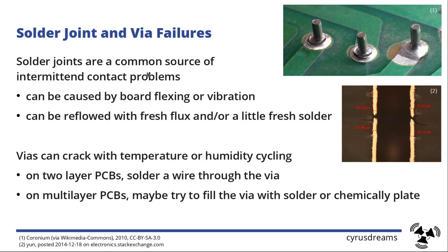The PCB board itself, it can also have some quite annoying failures. You have the solder joints everywhere, and over time, if there is vibration present or it's a very heavy type of component on the top side here, you get cracked solder joints. So you have these lines running around the whole solder joint. So that one on the right hand side, that's actually still connected. You do have something different here. You have pad lifting. You see that maybe that pad got lifted off from the PCB, but those two definitely are cracked through. You can fix that quite easily with a soldering iron. You just reflow that with fresh flux and maybe a little bit of fresh solder here, and the solder joint is good as new.